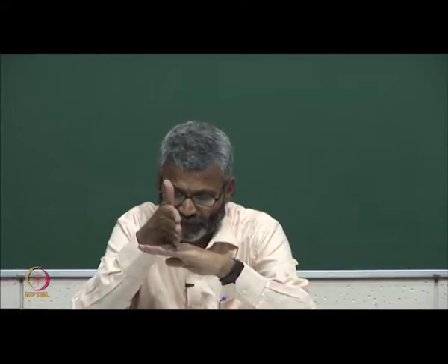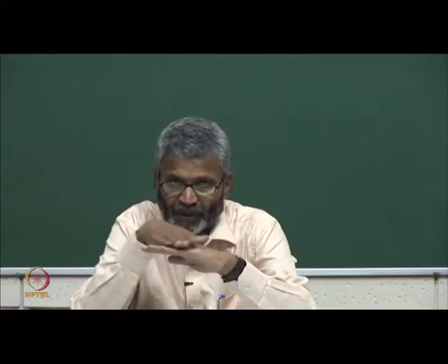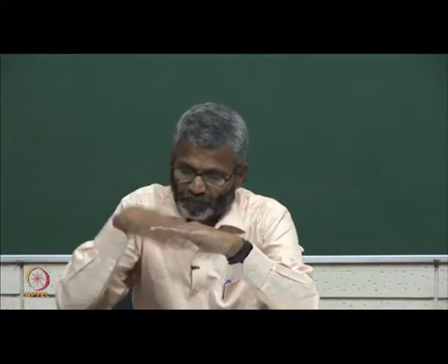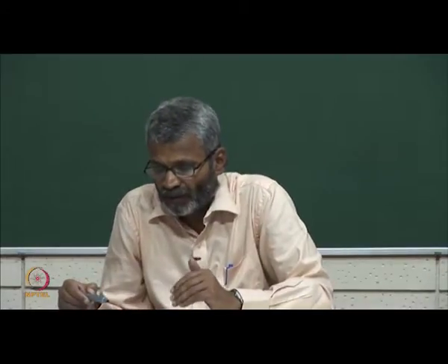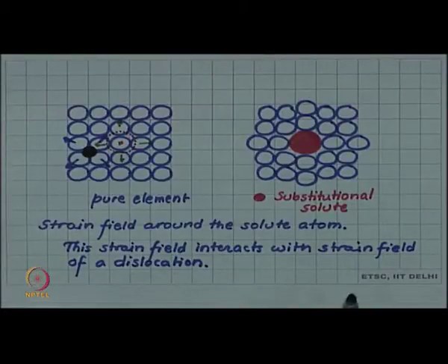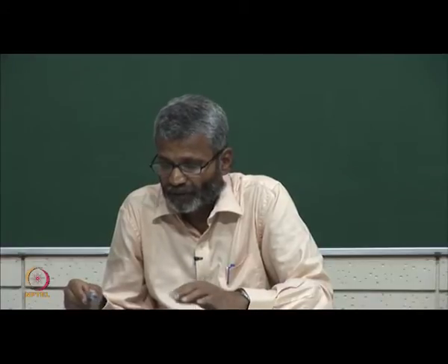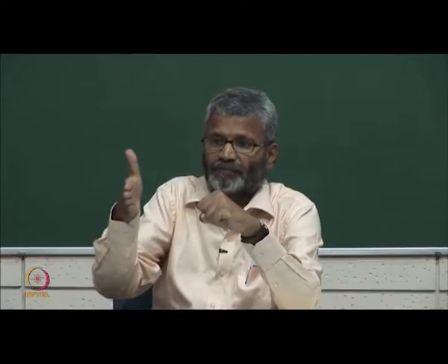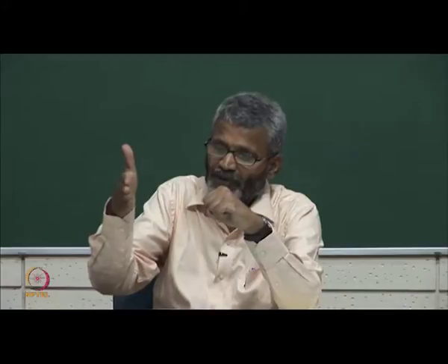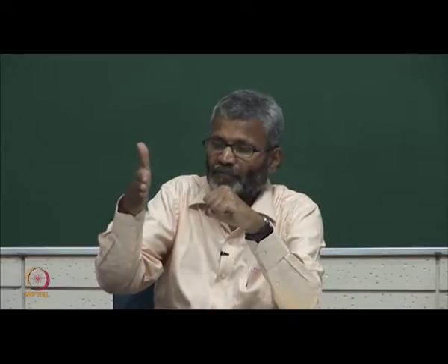Now, if the solute atom stress field interacts with this, and suppose the tensile and tensile overlap, this will cause an increase in the strain energy of the material and there will be a repulsion. So, the dislocation line will be repelled by the solute atom, and the motion will be impeded.